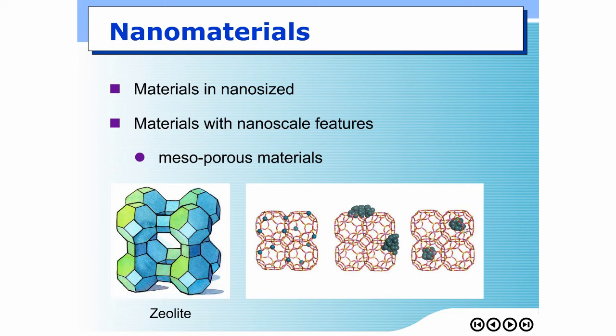Alright? For instance, if you have crude oil and you want to react some small molecules to something else, and you do not want reaction to take place for the larger, bigger molecules, you can put catalyst inside this small opening of zeolite so that only small reagent can access this catalyst and undergo conversion. Okay.